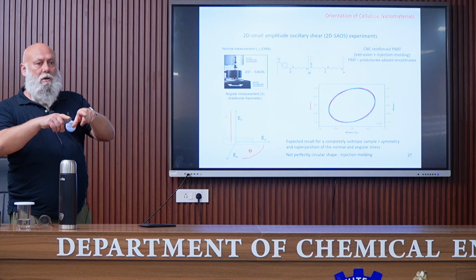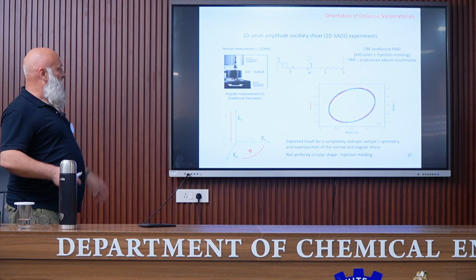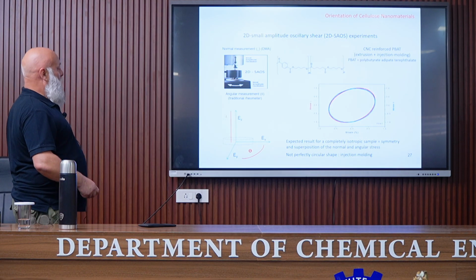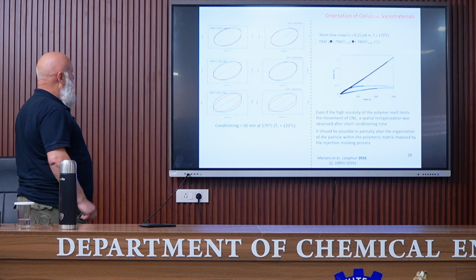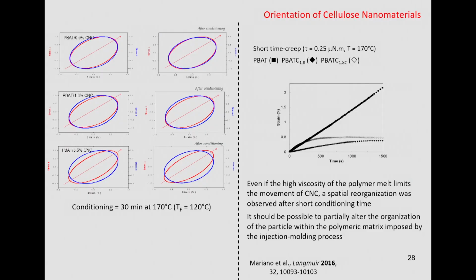We have some orientation of the macromolecule, and this is the reason why we don't have, let's say, a perfect signal. Then the experiment was performed with 0.9, 1.8, 3.6% cellulose nanocrystals. We can see that by increasing the CNC content, we have a bigger difference between the 2 stresses. So meaning that we have some orientation.